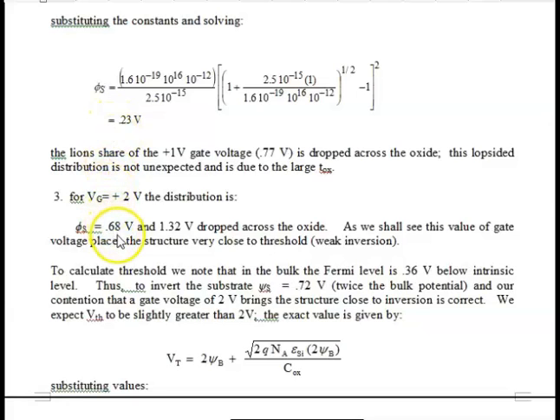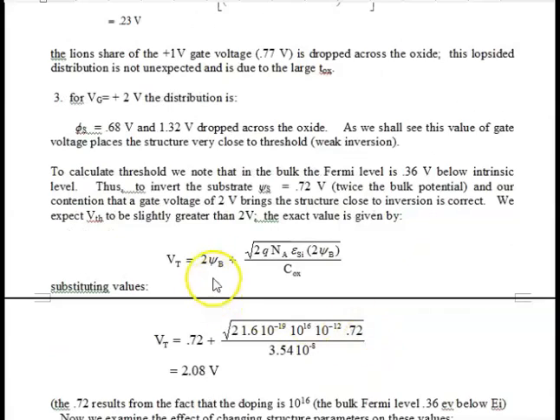So the band bending increases quite a bit more than we would expect. It's not linear by any means. We increase the voltage by 1 volt, and it increases by well over twice the bending that we had for the smaller value. And that places the structure very close to threshold, and we can prove that by calculating the threshold voltage. And that's what we do here.